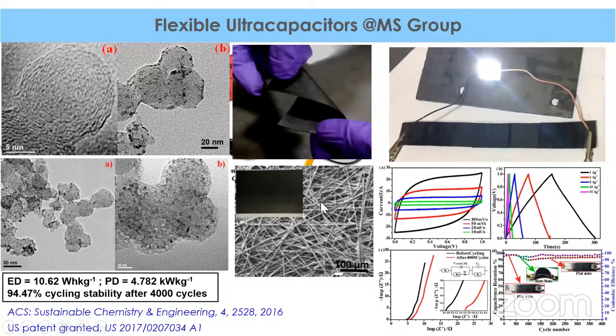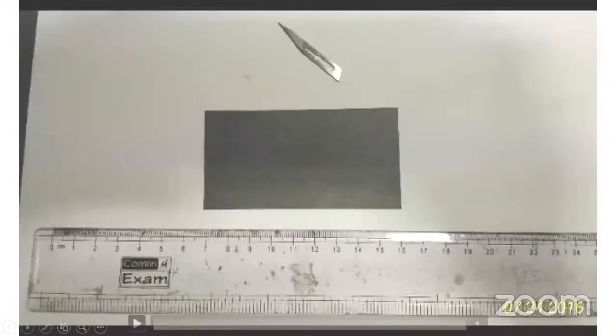So this is the conducting carbon paper. You can see that it is made up of small fibers. Using PDMS, he has made it flexible. This is his active material, which is ruthenium oxide and carbon nano-onions. And this is the final device that has been prepared. It was tested in different conditions, like flat state, bend test, and flattened again, for nearly 4,000 cycles. The capacity was regained when it was brought back to the flat state. We published it in a good journal, and we have obtained a patent for this device. In the next slide, I'll show you a small video on how this was prepared.